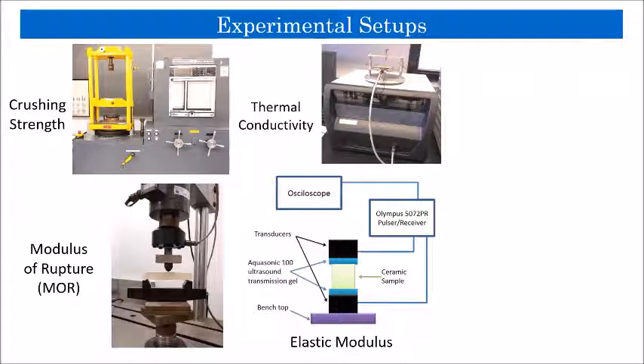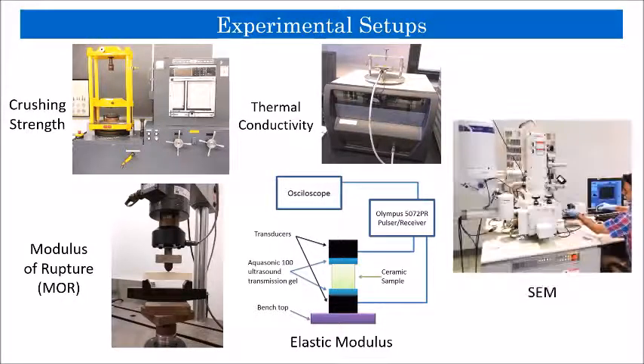Thermal conductivity of the matrix material was measured using ThermTest thermal conductivity measurement instrument. An electric furnace was implemented to apply a thermal shock cycle to samples, which comprised of a consecutive heating and cooling profile, or a hot shock followed by a mild shock. We utilized scanning electron microscope, or SEM, to view the microstructure of the samples both before and after thermal shock cycle.